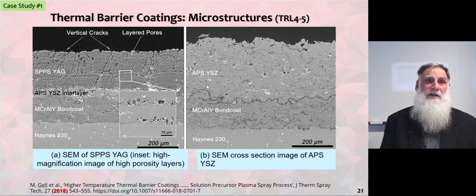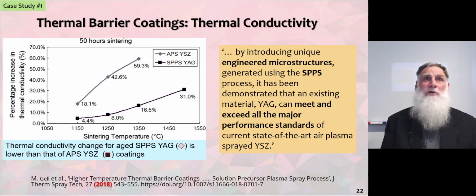What you're able to see is a very fine structure with vertical cracks compared to lamellar cracks in the conventional coating. So straight away, we see that there is a different functionality within the liquid thermal sprayed YAG coating. We still have an yttria-stabilized zirconia interlayer, the bond coat sprayed onto the superalloy. When we look at the thermal conductivity of these coatings, we see that those of the SPPS YAG, the liquid thermal sprayed YAG, are much better than those of the yttria-stabilized zirconia coating.